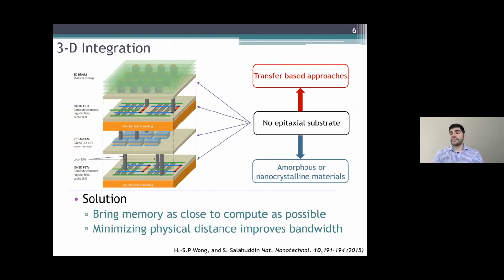However, because of this fact, if we take a silicon CMOS substrate and want to start building multiple layers of devices, especially at a large scale, you're not going to have epitaxial substrates on which to grow materials. So if we want to make multi-layer architectures, we're really left with two approaches. One is a transfer-based approach, where you grow a material and then transfer it to the substrate, and the second is an amorphous or nanocrystalline material deposition approach.